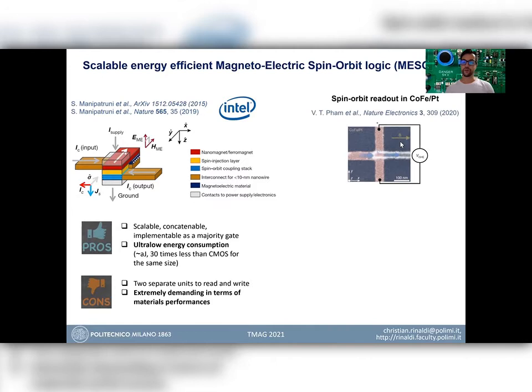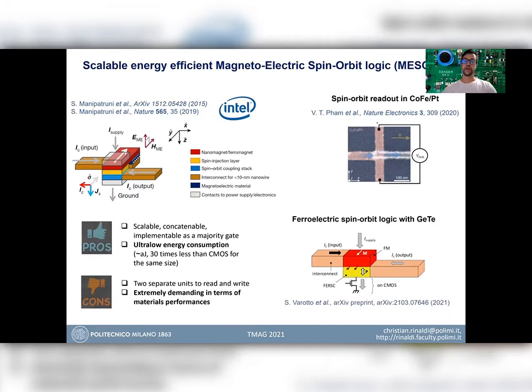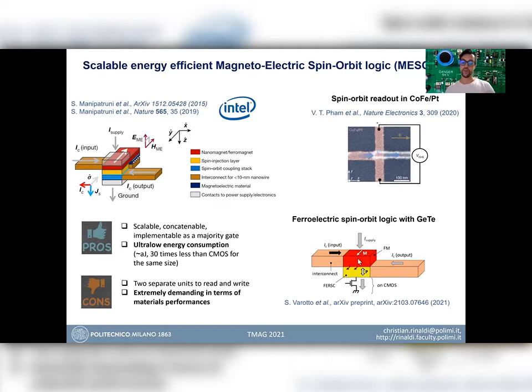The spin-orbit readout, one of the two building blocks of this structure, has been demonstrated in 2020 for the cobalt-iron and platinum couple, where platinum is the spin-to-charge conversion element. Nevertheless, realization of the full MESO structure is still far from realization. What I want to propose here is an extreme simplification with a different logic, which could be called ferroelectric spin-orbit logic, relying on germanium telluride or similar compounds, where information is stored not in a nanomagnet's ferromagnetization but in the ferroelectric polarization directly.